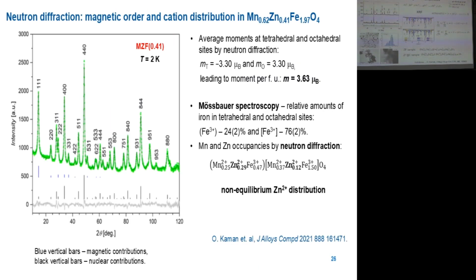Another powerful tool is neutron diffraction. Again, we don't have time to go into details, but this can help to resolve even more complex situations. For example, we mentioned the manganese zinc ferrite, which contains three different metals. If you are interested in the real cation distribution between the tetrahedral and octahedral sites in this spinel structure, you should consider measuring neutron diffraction, because even if you measure XRD and Mössbauer spectroscopy, you cannot resolve the situation.